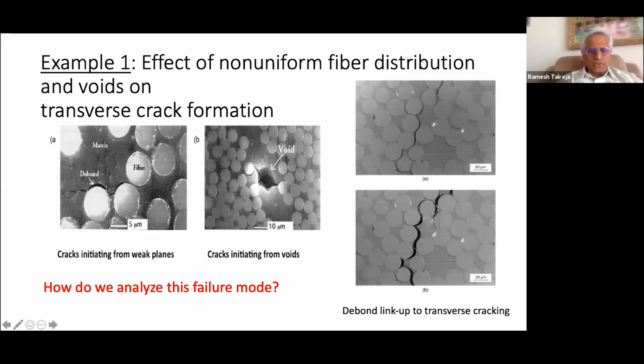These images here show you that when you look at any instant in a cross-section of a UD composite, you see a fiber debonded from matrix, you see a crack in the matrix, and it may be that the debonding occurred first and proceeded as a matrix crack and joined the next debond, or that in a resin-rich pocket, a crack formed in the matrix, went to the fiber surface, debonded it, and proceeded that way. So those are the issues one can resolve through failure analysis.